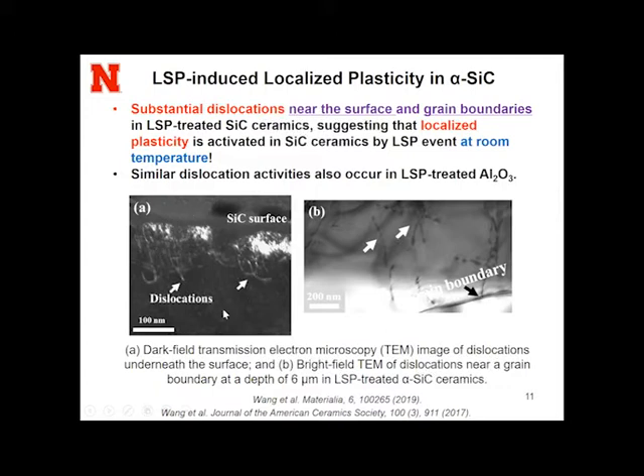So here, the left shows a cross section TEM image. This is a weak beam dark field image, and you can see a high density of dislocation near the surface. And the picture on the right also shows dislocation occurs even at a depth of 6 micrometers and near some grain boundary. All these results are surprising because what we are doing here is LaserShock peening at room temperature, and the common knowledge is that ceramic is very difficult to activate dislocation slip at room temperature. So we call this localized plasticity in ceramic, because the plastic deformation by dislocations is localized near the surface and grain boundary.